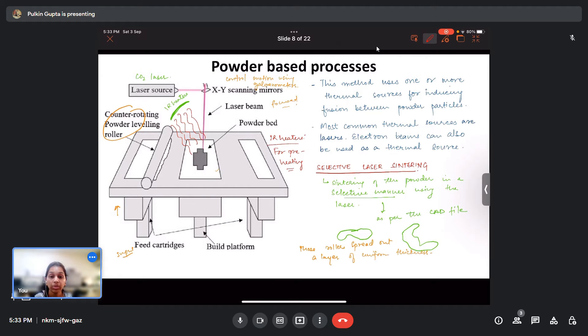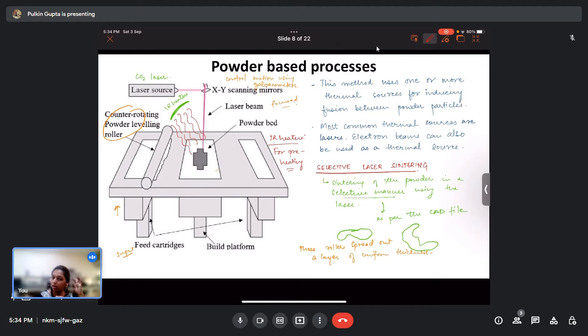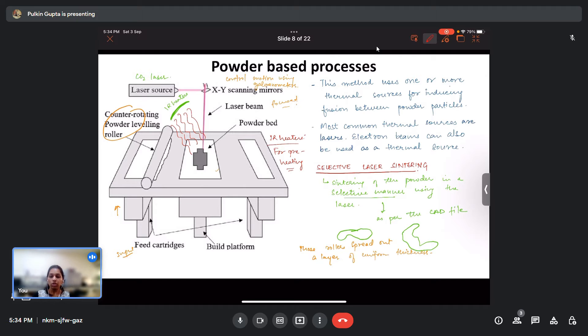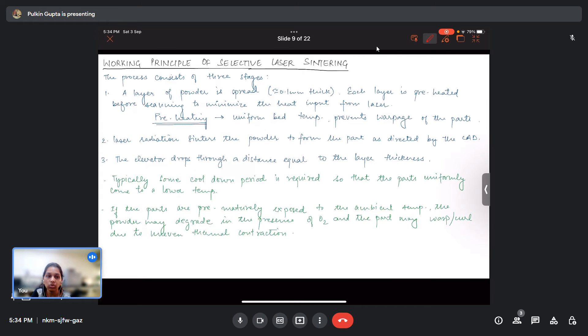When the laser strikes the powder, temperatures are very high. Such a steep rise from room temperature to those high temperatures can create very sharp thermal gradients, which eventually lead to high residual stresses within the manufactured component. To avoid such residual stresses, the powder is preheated so it attains a certain elevated temperature before the laser strikes it, reducing the thermal gradient and thus avoiding sharp thermal stresses.